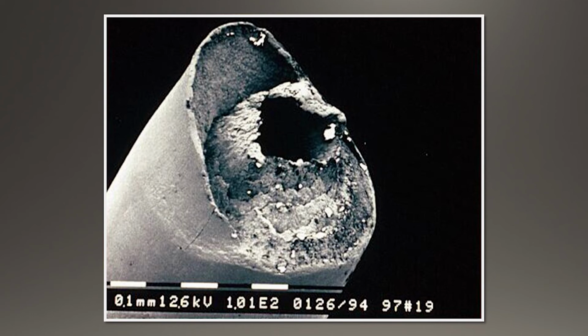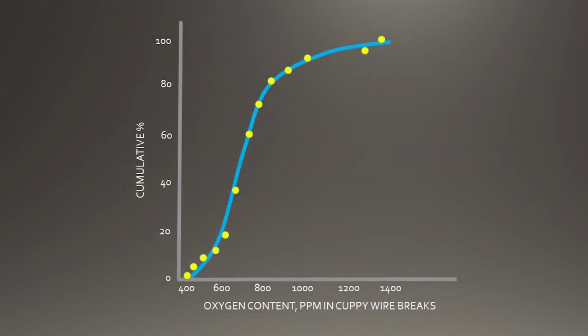But inside, there's a little void. There was some macro porosity, which exacerbated and caused this cuppy end of the wire break to take place. This happens to be a curve only for copper. It shows that the amount of wire breaks increases as the oxygen content gets too high. Oxygen is not the cause of the problem, but it means with higher oxygen content, it makes the wire less ductile, more brittle, and cracks are more easily likely to form and to propagate more easily. So again, it's not the cause, but it makes the wire break occur much more easily.